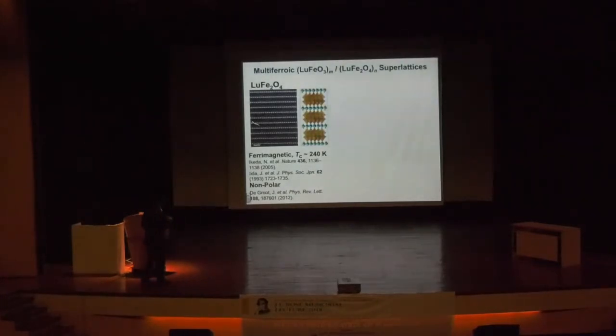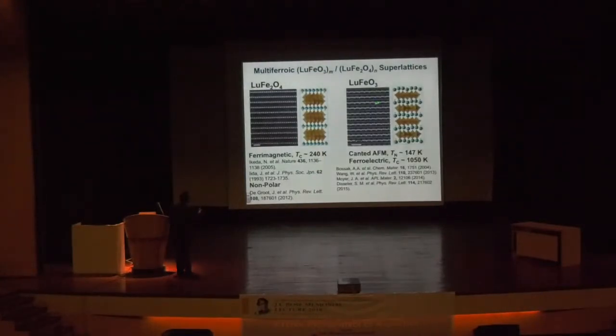Right? If you look at this compound, lutetium iron oxide spinel, it's not a spinel, it has a related structure. It is very magnetic with a TC of about 240 Kelvin. It's nonpolar. There was a lot of debate about 10 years ago whether it was a polar compound or a nonpolar compound. Now everybody is agreed that it's nonpolar. If you look at its sister compound, 113 compound, that is a canted antiferromagnet with a TC of about 140 Kelvin, but it's a very good ferroelectric. It's a TC of about 1,000 Kelvin. The polarization is very small.